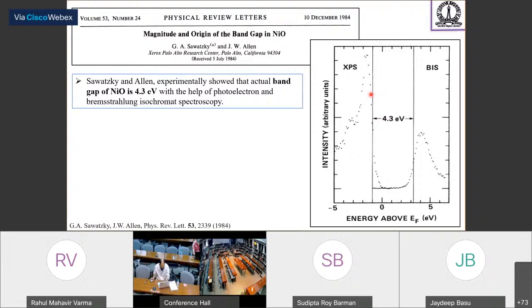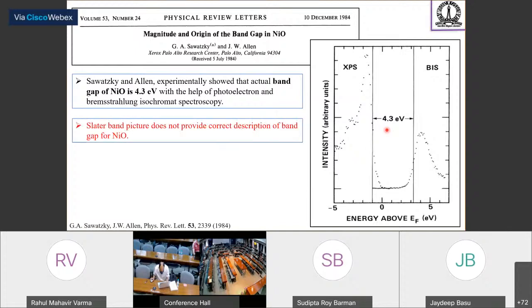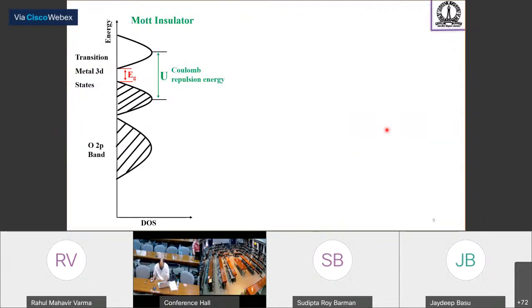who did the photoelectron and Bremsstrahlung isochromat experiments to measure the valence band and the conduction band, and they showed the actual band gap of nickel oxide is 4.3 eV, and hence the Slater band picture does not provide the correct description of the band gap for nickel oxide. For a long time, it was not clear why the band gap of most correlated systems is not being given by the Coulomb energy term U.